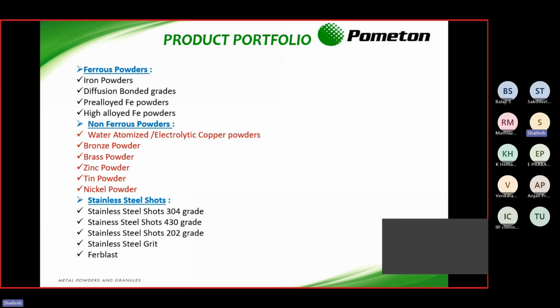Basically, Pometon manufactures both ferrous and non-ferrous powders, and also stainless steel shots in the product portfolio. In ferrous powders, we have different grades of iron powder: high alloy, pre-alloyed iron powder, diffusion bonded grades, and plain iron powders. In non-ferrous powders, we have different grades of copper, brass, bronze, zinc, tin, and nickel. And for stainless steel shots, all grades of 304, 430, and 202 stainless steel for blasting are available in the product portfolio.